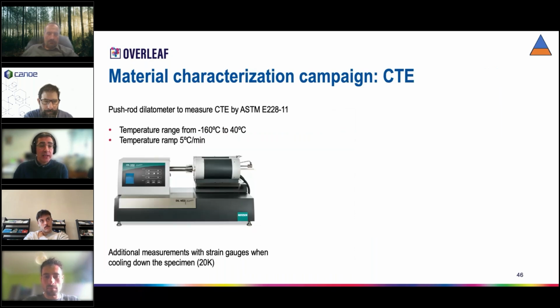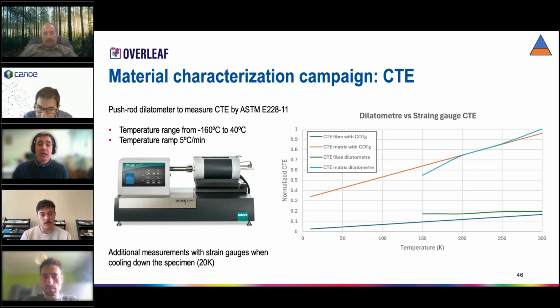And finally, we have characterized the thermal expansion coefficient by two methods, with the push rod dilatometer. That is a typical equipment, but this equipment is limited to a range of temperatures, minus 160 degrees to 40 degrees. So we have performed additional measurements with strain gauges while cooling down our specimens. On the right side, we have a couple of graphs with the thermal expansion coefficients with respect to the printing direction, and also perpendicular to the printing direction, with a dilatometer that ends at this point, and with the strain gauges so we can reach lower temperatures. We can see that this thermal expansion coefficient is not constant for this material. It's more or less constant in the printing direction, as Canoe showed, but perpendicular is not. So we have to take this into account in our analysis.